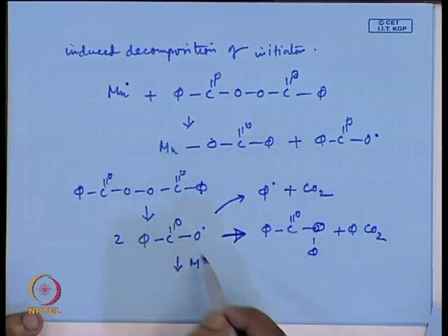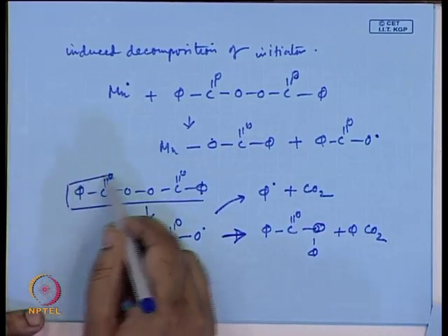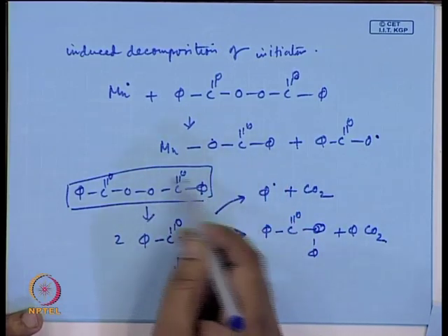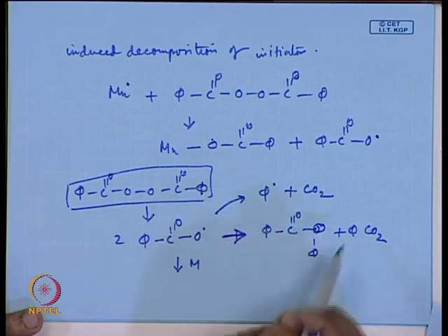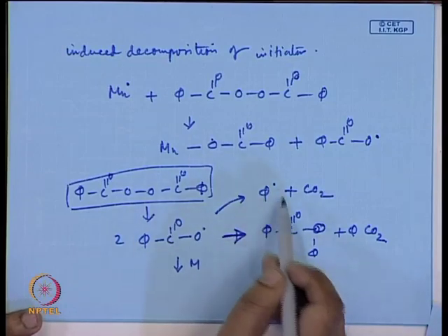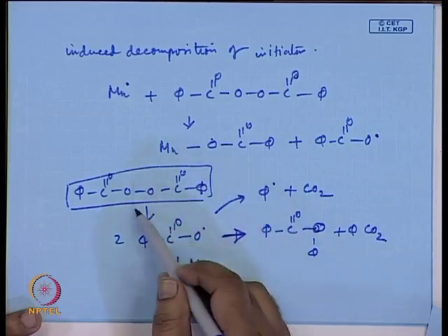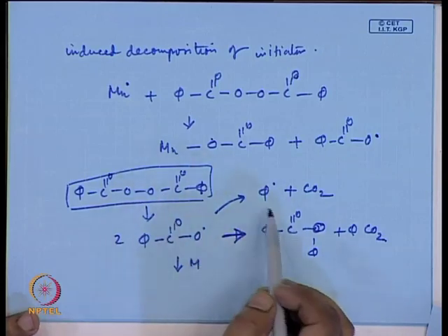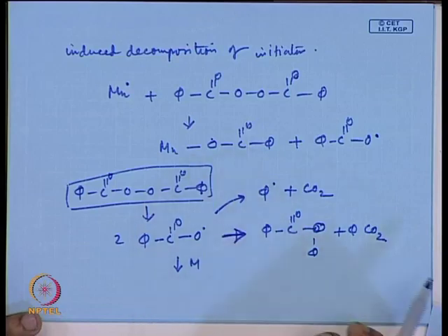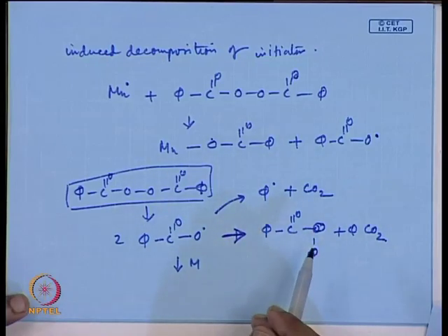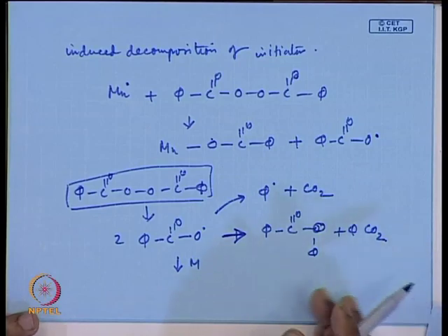So, if there was no side reaction, the amount of radicals it were generating, now it has reduced because of these so many side reactions. In other words, all the radicals which are getting generated by homolytic cleavage of this benzoyl peroxide are not initiating a chain, which means they are getting lost in doing non polymerization reactions.